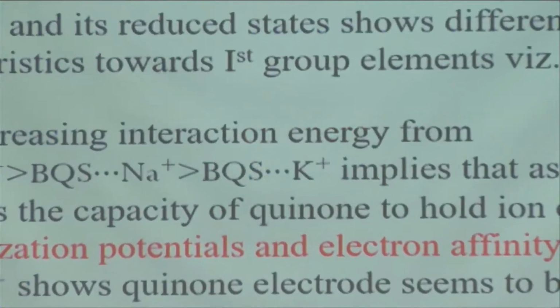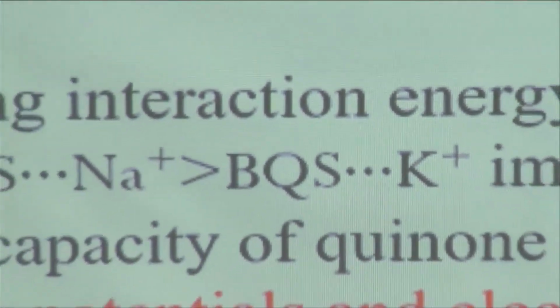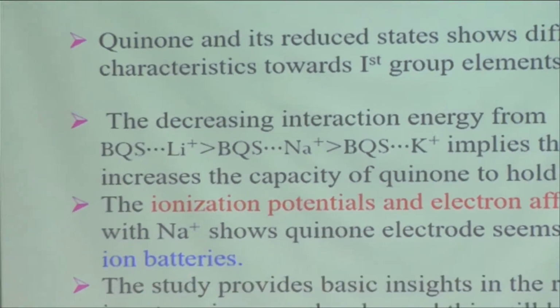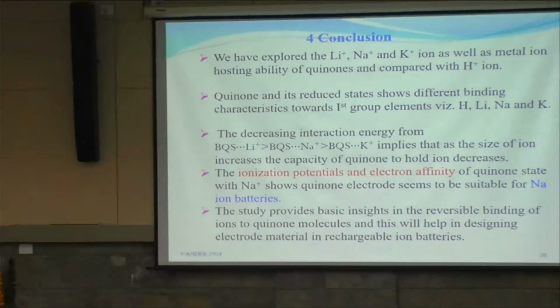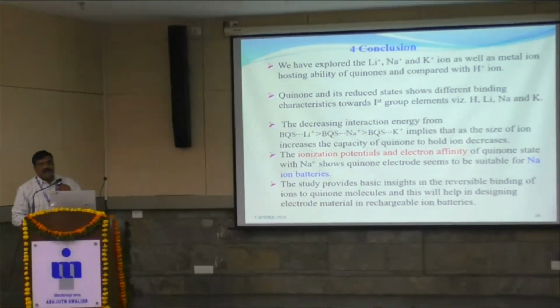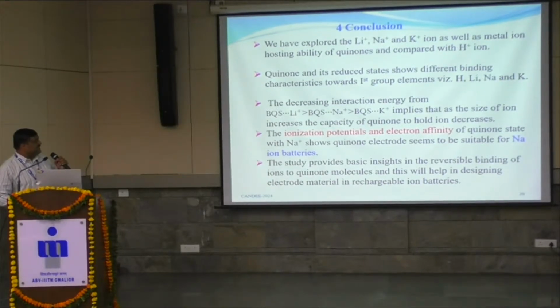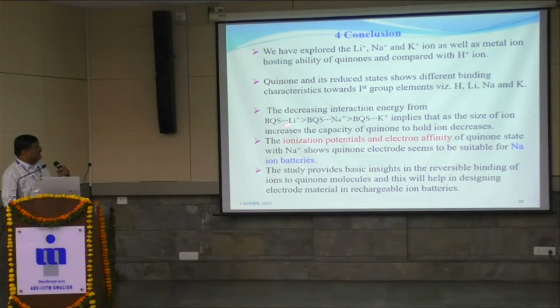From this, we conclude that we have explored lithium ion, sodium ion and potassium ions as well as metal ions' binding ability with quinone as compared with the H plus ion. Quinones and their reduced states show different binding characteristics towards first group elements: hydrogen, lithium, sodium and potassium. As interaction energy decreases across these complexes, the benzoquinone state with lithium complex and with sodium complex is better as compared with the potassium complex, implying that as the size of the ion increases, the capacity of quinone to hold the ion decreases. But ionization potential values and electron affinity values of the quinone state with sodium ion show that quinone seems to be suitable for sodium ion batteries.